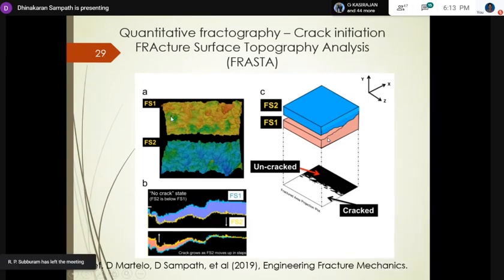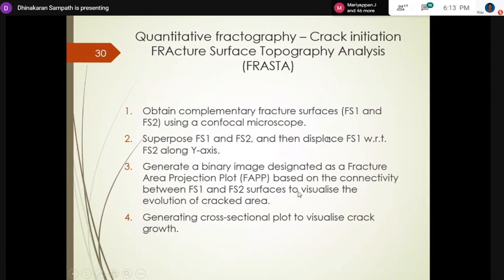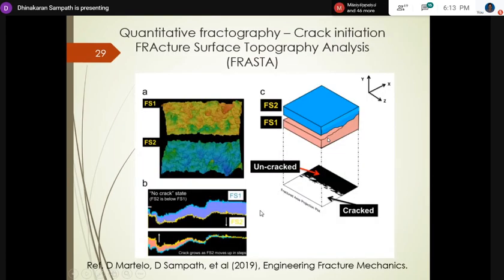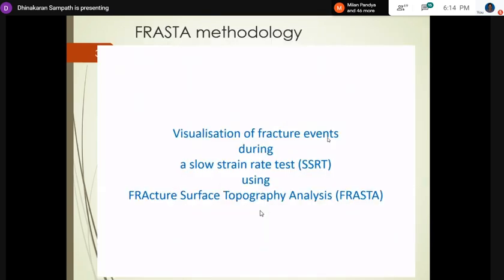So what we did was take the topography of the fractured surfaces, the complementing surfaces, and fix one surface, and then pull one below that, so that it simulates the no-crack state. Then lift the FS2, in this case, and move it upward in steps, and then we see the connection between them. When the points on the surface are above the fixed one, they will be marked white, and those points that are below the fixed surface will be marked black. So we get a binary image, which is called the fractured area projection plot. This is the procedure explained here, and this is what we use to see how the crack evolution occurs from the topography.